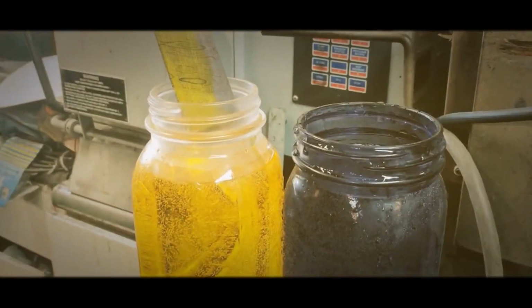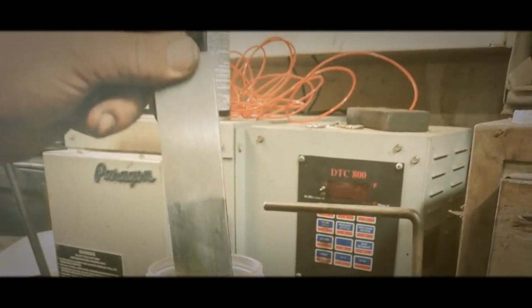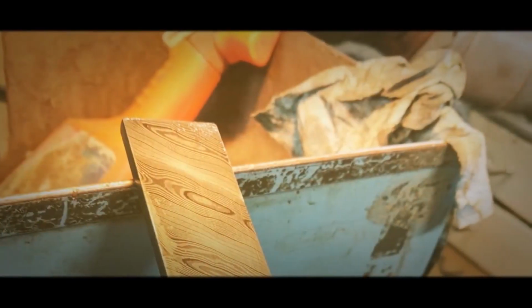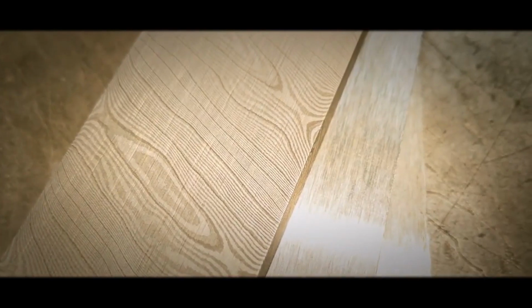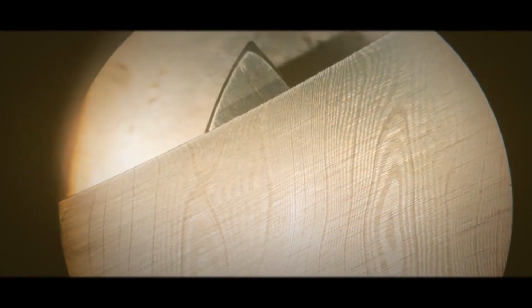What we do is we acid etch, and there's several different acids that work very, very well. The two most common ones that most people have heard about are muriatic acid, which you can buy as a brick and concrete cleaner right at your favorite big box store that sells construction supplies. The other is ferric chloride, and ferric chloride is known as an etchant for circuit boards.